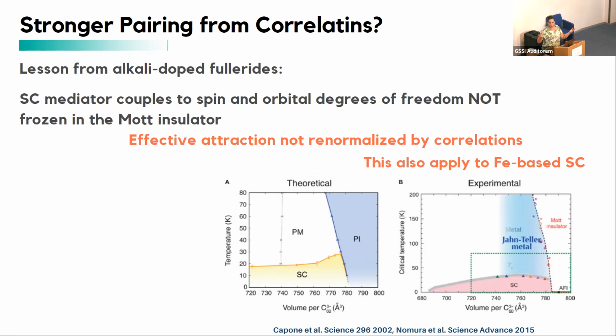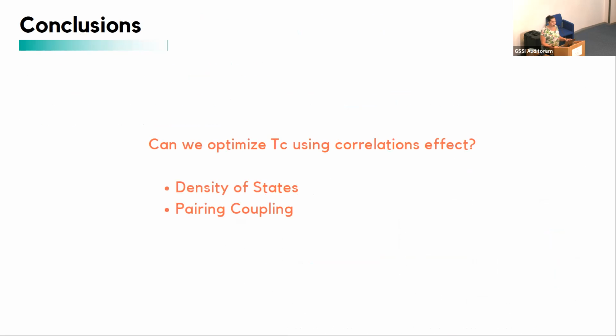Essentially, I'm going to put it in simple words, of course, it's more complex than this, but the idea was that the superconducting mediators in this system couple to spin and orbital degrees of freedom that are not frozen in the Mott insulating phase. What is frozen in the Mott insulating phase are charge fluctuations. So whatever superconducting coupling is mediated by these would, of course, be damaged by the presence of correlation. But the idea is that in iron-based superconductors, the pairing would be mediated by spin fluctuations that are actually not damaged by the presence of correlation. So these are my conclusions.